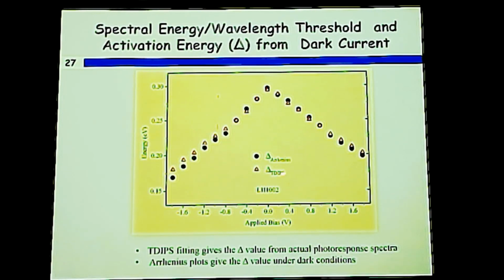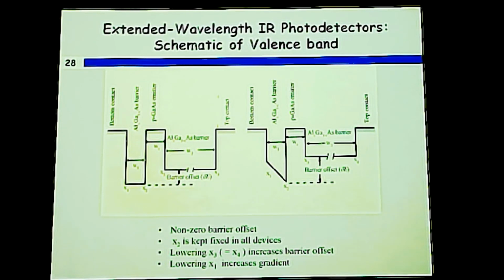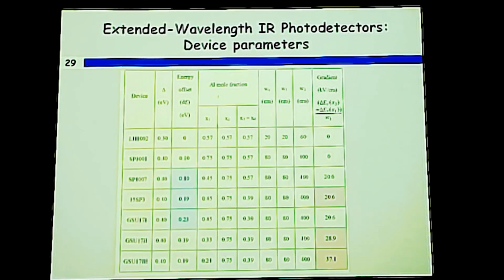So these triangles are from Dilip's method, from the photoresponse, and these Arrhenius are from the dark current. These are the devices for the extended wavelength mechanism. We have barrier offset. One device has a constant barrier, and other devices have a graded barrier, and the barrier offset is changed in different devices by changing this aluminum fraction, and the gradient is also changed by changing this aluminum fraction x1 in the graded barrier. So here is the table showing the different values.